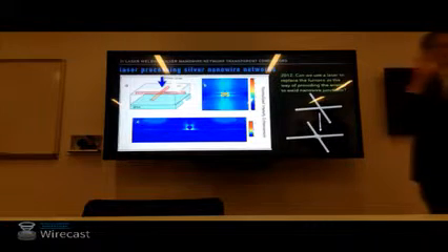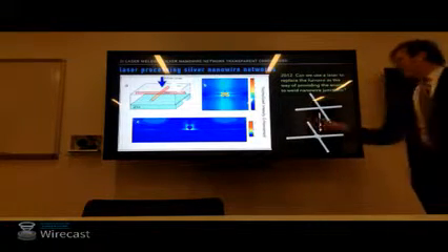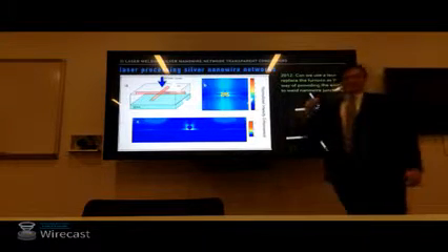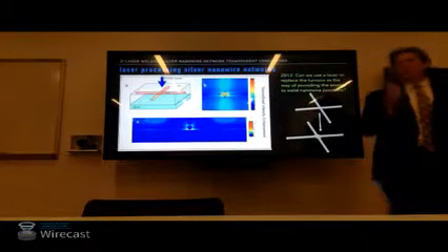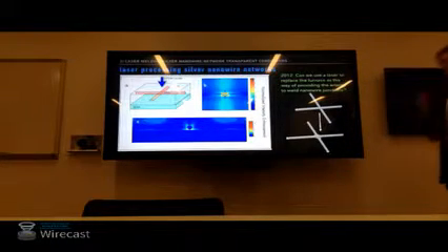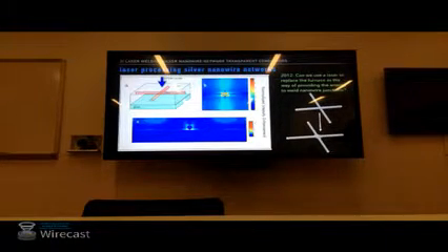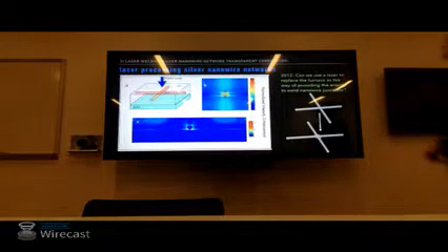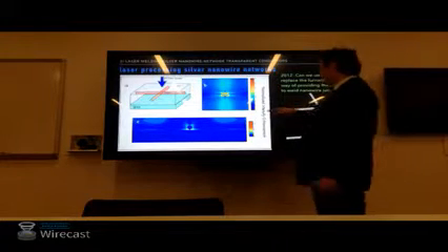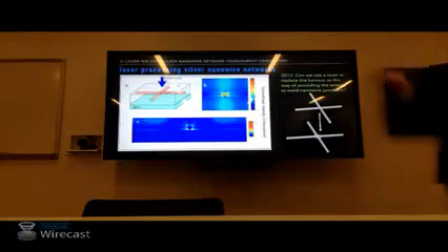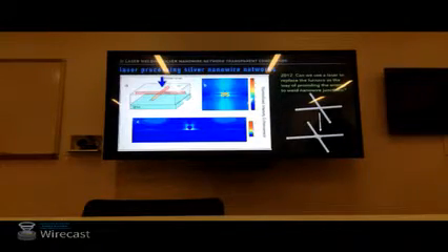Now, this wasn't totally a pleasant surprise. We suspected this is what would happen because that area, that junction between nanowires, is a highly scattering area. When you have that high scattering, you tend to be able to trade energy into the material, trade a photon for a plasma oscillation in your metal, or plasmon. So we see about a 10-fold increase in intensity. But as I mentioned, we have 4 of these lasers, so why don't we just do the experiment?